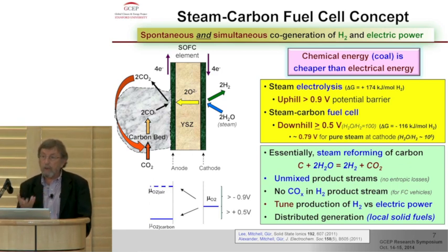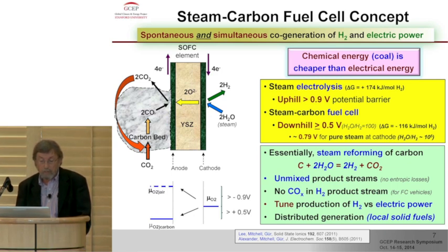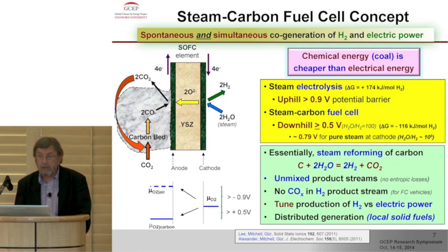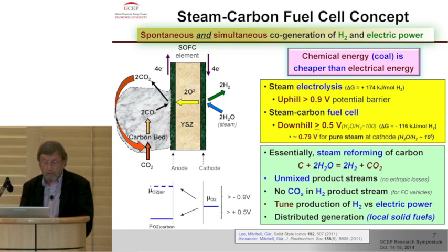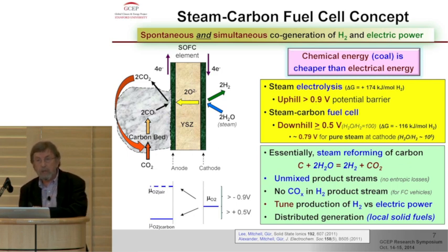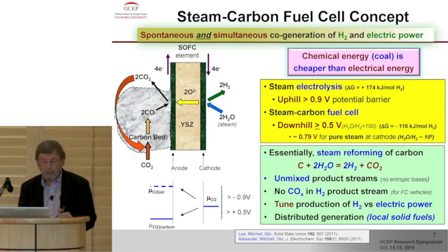This provides a driving force downhill for the oxygens to be stripped from the steam, transported through the electrolyte, and be oxidized at the anode side. And so we're turning an electrolyzer. Steam electrolysis requires anywhere from 0.9 volts to 1.3 volts, 1.23 volts at room temperature, depending upon the temperature regime. It's a very high activation barrier splitting process. We turn an electrolyzer, which requires electricity to do chemistry, into a fuel cell, which produces electricity as well as a fuel.